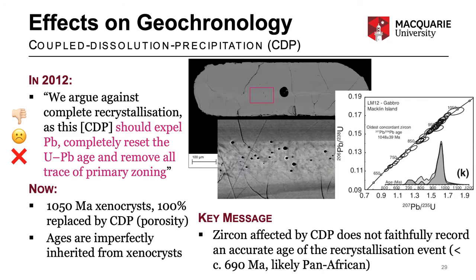In 2012, we argued against complete recrystallization, as this coupled dissolution precipitation should expel lead and completely reset the uranium-lead age and remove all trace of primary zoning. I think back then we got it wrong. I think this process of coupled dissolution precipitation can form such an ultra-local chemical environment at the dissolution precipitation reaction front that the uranium-lead character of the precursor grain can get copied, or at least partly copied, to form these complex spreads in ages.